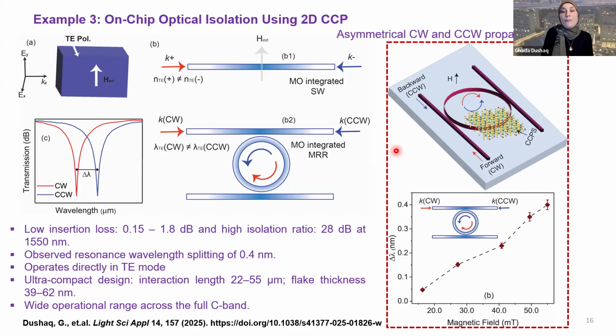And for this specific application, we use it as an optical isolator, which is a very vital element in photonics, because when you have an integrated laser, you always have a back reflection that can add to the signal noise and can damage the laser. So you want to prevent the back reflection by having a straightforward laser going on without having a back reflection. So basically, this is what this element can do. It's just preventing the back reflection by having a non-reciprocal kind of performance.